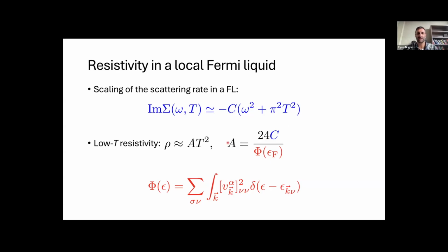And you can actually rewrite in a very compact form the coefficient of the T-squared resistivity with respect to this coefficient of either the frequency or the temperature scaling. And the only part here that comes from the DFT calculation is the so-called transport function evaluated at the Fermi level. You can think of this as the Drude weight. So basically, we can boil down the problem of calculating the resistivity in the Fermi-Liquid regime, at least, to calculating this coefficient C.